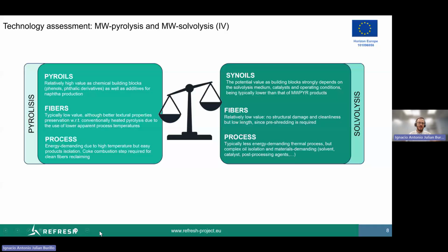So comparing both pyrolysis and solvolysis, we have three categories for comparison. So the oils, the fibers, and the process itself. In case of pyrolysis, the oils have a relative high value as chemical building blocks. Phenols and phthalic derivatives products are obtained, and they can be used as additives for naphtha production, as said. Regarding fibers, they have typically low value, although better textural properties preservation with respect to the conventionally heated pyrolysis process due to the use of a lower apparent process temperatures, and the process itself is energy demanding due to the high temperature, roughly 400 to 500 degrees Celsius.